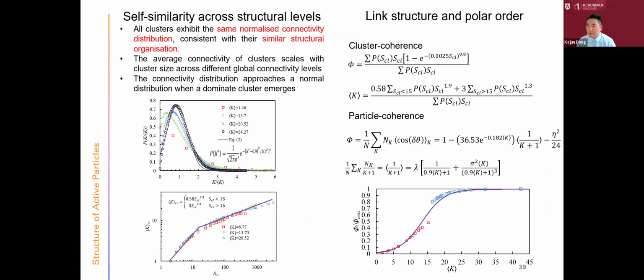And we also find something very similar to the microstructure universality. We find some structure universality or self-similarity at different scales in the Vicsek system, including the cluster level and the global level. The distribution of the connectivity shares the same normal distribution pattern. And using this, we also see that the cluster's orientation can be characterized with its size in a universal way. With that, we can predict the system's behavior, here the global order from its structure. So it also proves that in another particle system, the active particle system, the structure has laws. And if you understand these laws, you can derive the system's performance based on them.